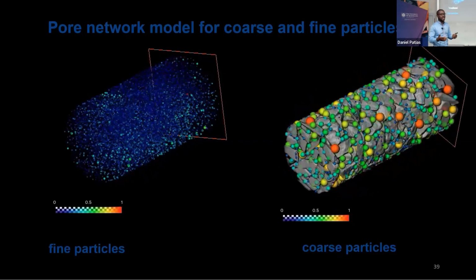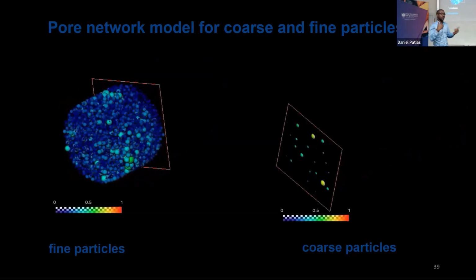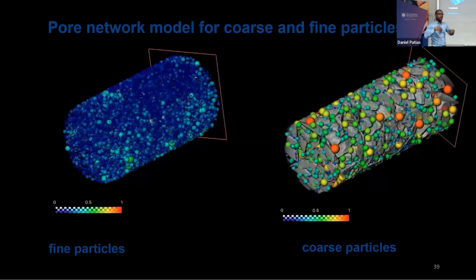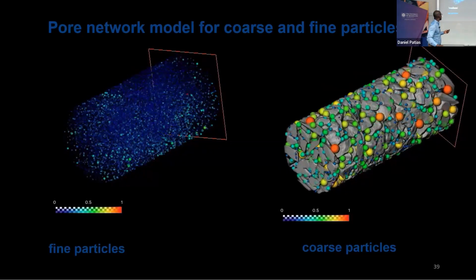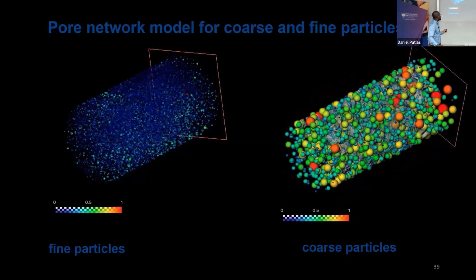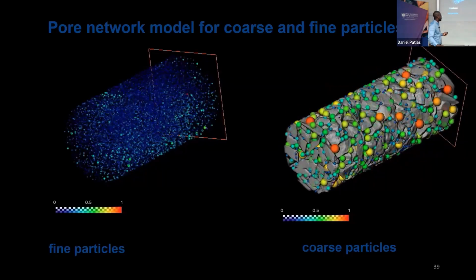So we want to understand quantitatively the influence of this precipitate, or jarosite, that's forming on the pores and the connectivity throughout the column or the heap. For the fines, you see there are virtually very small pores, whereas for the coarse material, you have very big pores.